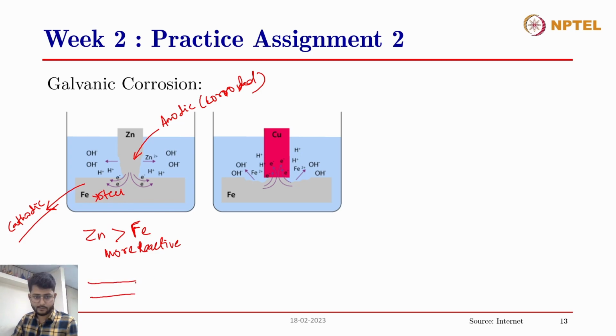let's say this is the steel, and this is the zinc layer. Even if there are surface scratches on the steel, still due to the galvanic protection, or this galvanic corrosion process, the zinc will keep on corroding. Even if there is a small amount of zinc present at that location over the steel reinforcement, that zinc will corrode before the steel gets affected. So this is the galvanic protection that is being talked about in this statement.